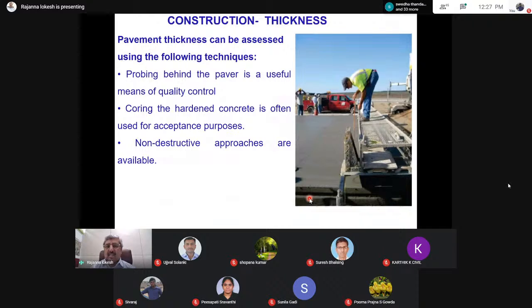So this is another check that can be done while paving. This is the concrete paving and this is the paved concrete surface. We can stand behind the paver and, using a probe, check the thickness that we have laid. This is once again done once the concrete is laid. And coring can also be done once the concrete is set, after 28 days of hardening, to assess the strength as well as the thickness of the core. Non-destructive tests are also available to assess the thickness as well as the placement of dowel bars.